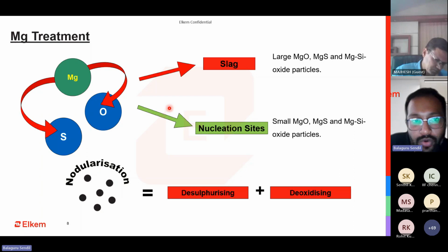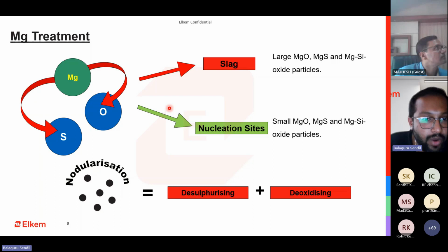If it is coming below a certain level, also it is risk. So ideally, you should have a target of 0.008 to somewhere between 0.015 in your base, which is the correct amount of magnesium required. When you have excess amount of sulfur, then you need to have a higher magnesium. I will come down to all that in the later upcoming slide, but this is the basic of how the magnesium treatment happens. We know when we are introducing magnesium, we are able to alter the speed.